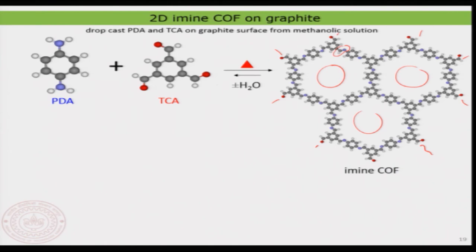To correct these defects, you do the chemistry not just in a dry atmosphere but in a moisture atmosphere — at equilibrium conditions. If a pentagon has formed, you can open that bond again by adding water molecules into the network, basically returning to the precursors. You can keep correcting, which helps propagate the two-dimensional structure over a larger area. Otherwise you always get small domains of the 2D network.